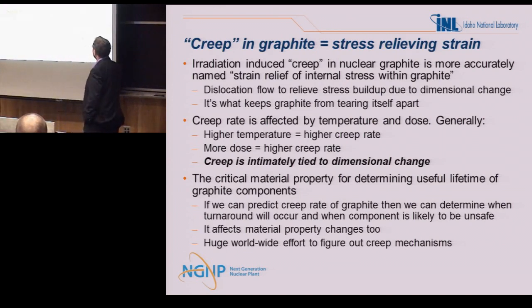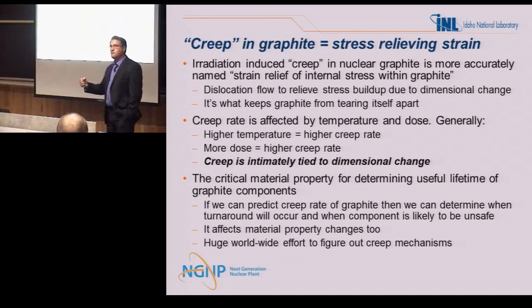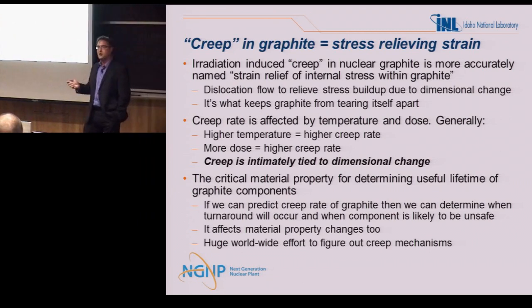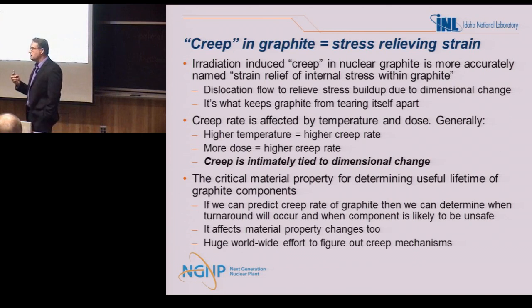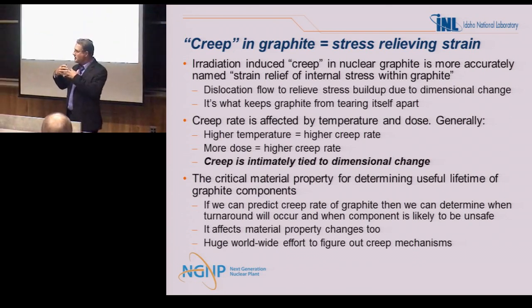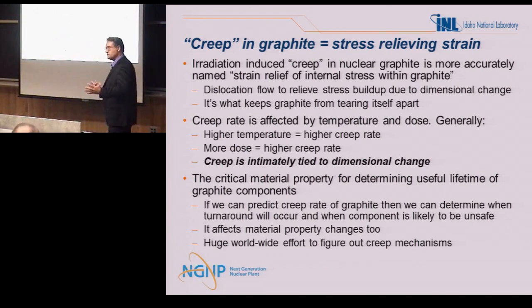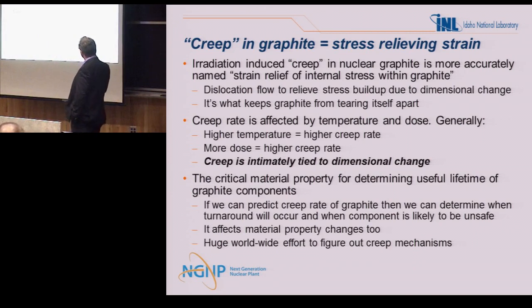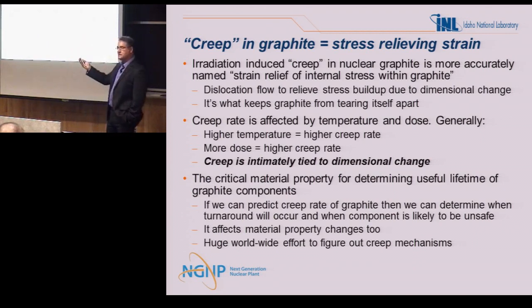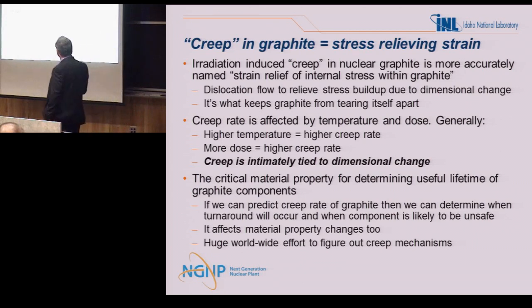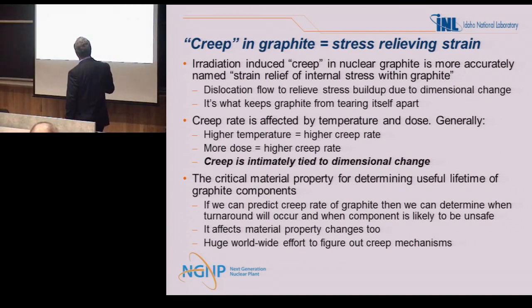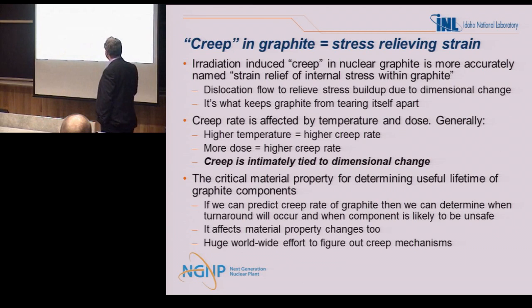Okay, creep. Creep in graphite is the key to longevity of the graphite cores. It is a misnomer. Those damn metal material scientists, they gave us the wrong word. What it really is, is stress relieving strain. Okay? As the stresses build up, the graphite actually displaces material, strains, and relieves those stresses. Like idiots, ceramic and graphite engineers took creep because it looks like metal creep, and it's just screwed us ever since. Anyway, so what's happening is dislocation flows in the graphite to relieve the stress buildup due to the dimensional change. All right, so creep is good for us graphite types. So again, because we're backwards. Okay, it keeps the graphite from tearing itself apart.